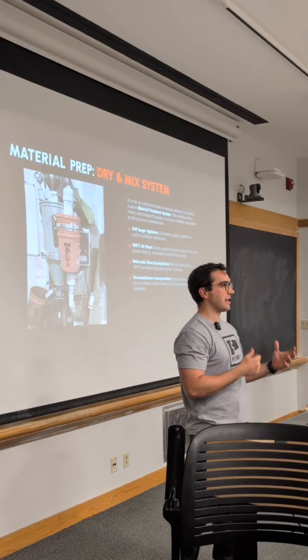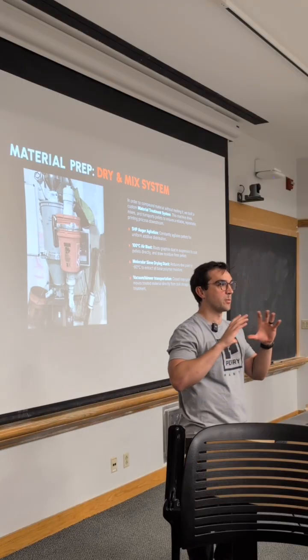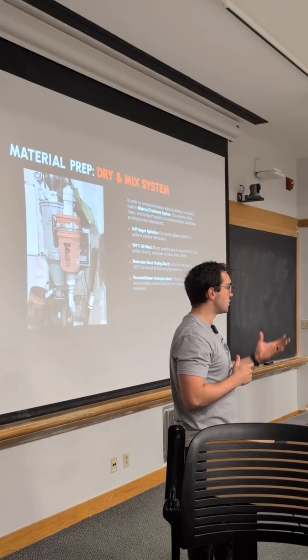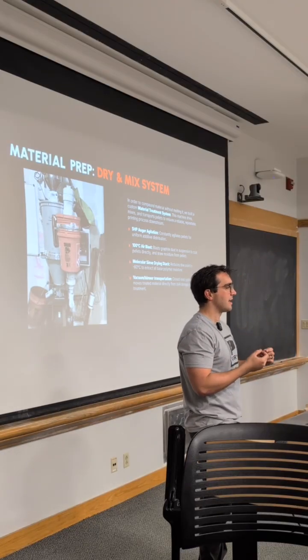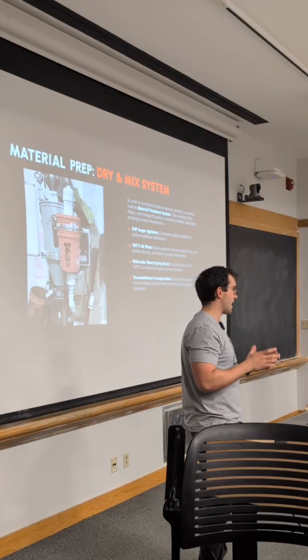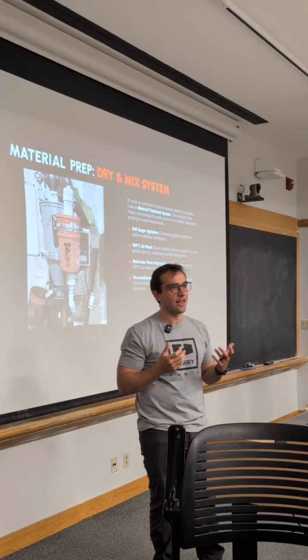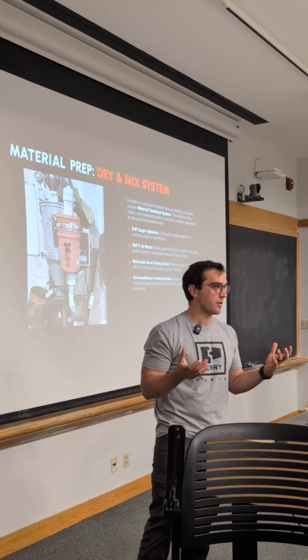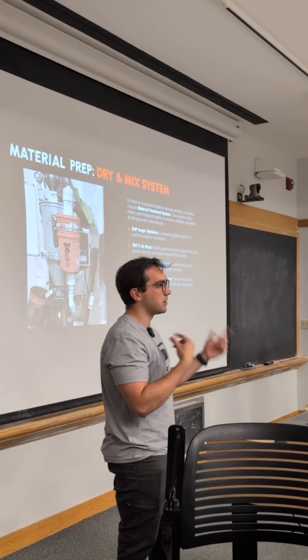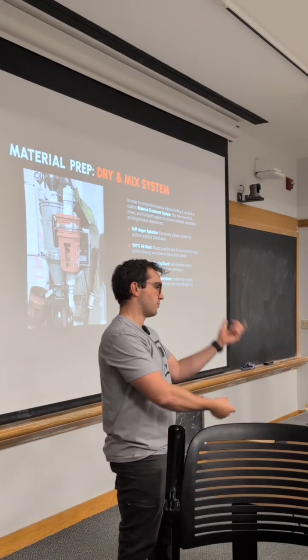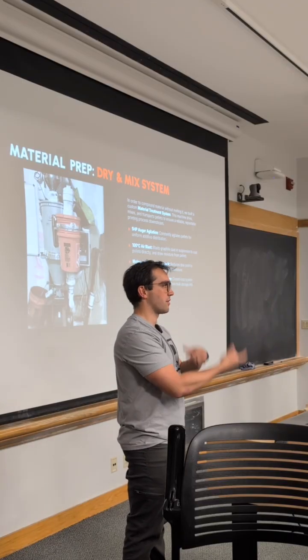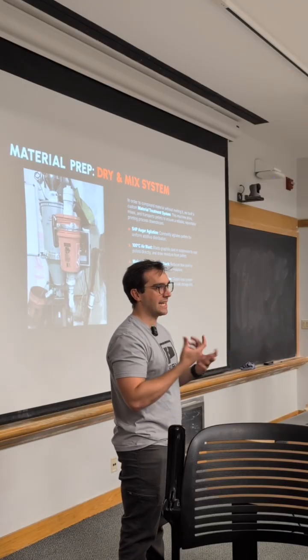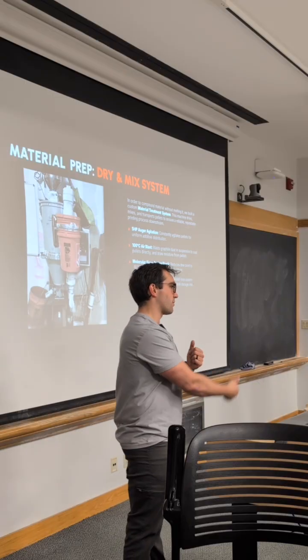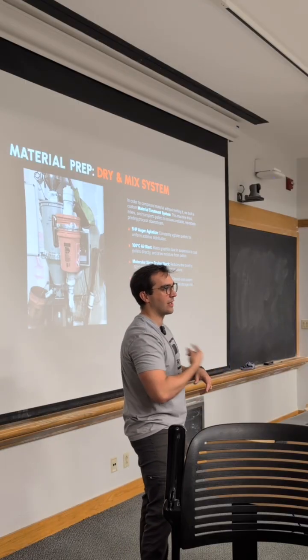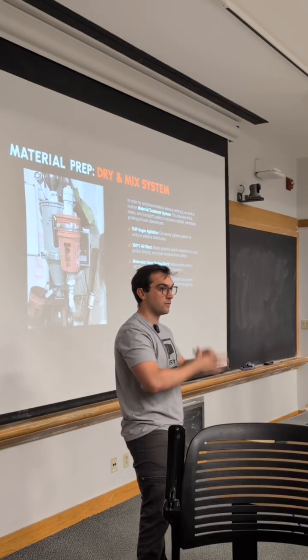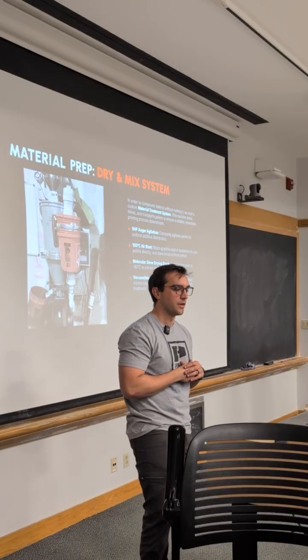The reason for that is twofold. One, to provide uniform drying throughout the chamber, and two, to ensure that the graphite is distributed evenly throughout the entire stack. On top of that, the entire thing is heated up to 100 degrees Celsius, so it's a closed loop, closed cycle system. We pull hot air through, there's a PID loop temperature controller that heats it, and then feeds it back through the bottom. And again, this is all being agitated simultaneously, so you get a really good uniform temperature gradient throughout the chamber.